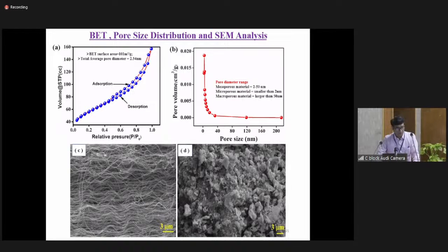As I was talking about, not only the surface area, some other parameters also play an important role. One is the pore diameter. Here the pore diameter was around 4 nanometer, and here the pore diameter is only 2.34 nanometer. When we measure the diameters of the dyes, the methylene blue diameter is around 1.1 nanometer, and the Yosun yellow is around 1.6 nanometer. So when both dyes have a diameter in the range of 1 to 2 nanometer, if the pore diameter is close to 2 nanometer, then it will be better.